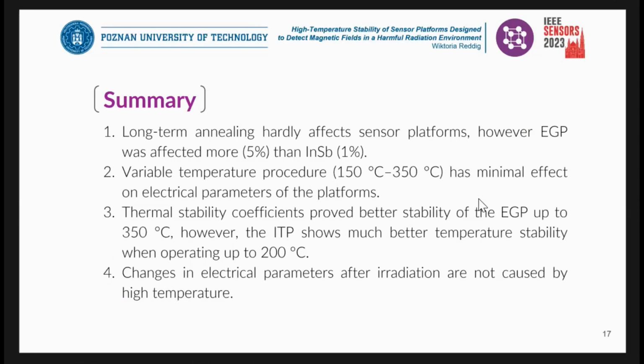And that will bring me to the conclusions that the long-term annealing and the variable temperature procedures do not really affect our sensors. The thermal stability coefficients prove better stability of the graphene up to 350 degrees Celsius. However, if we just take this range up to 200 degrees Celsius, it is the indium antimonide that has better temperature stability. Overall, however, we can see that after this irradiation, the changes that we measured were not caused by high temperature, but the radiation.